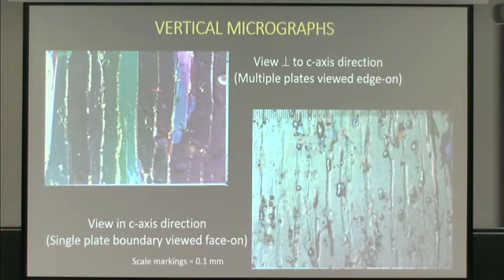So this view is looking at the book when it's closed, edge on. So you see your pages of pure ice, and then each page has this really complex system of brine inclusions on it. One of the things that happens when ice grows this way, for reasons I don't understand but I've fully characterized, is that the dislocation density is extremely high as a result of the growth process.